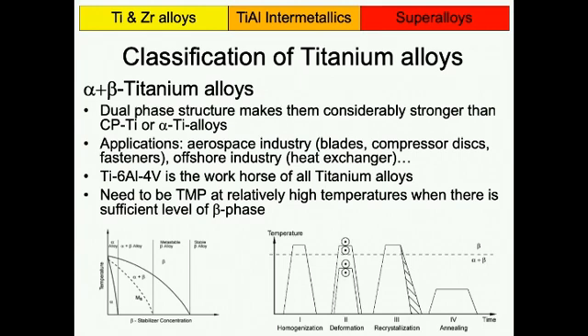And the grain refinement can be quite effective because of the two phases. They are widely used by the aerospace sector, but also by the offshore industry. So essentially, whenever you need higher strength, you use those. And as I've already mentioned a few times, and you should be aware of that, titanium 6 aluminum 4 vanadium is the workhorse of titanium alloys. So if there's one alloy I would like you to remember, it's this one.